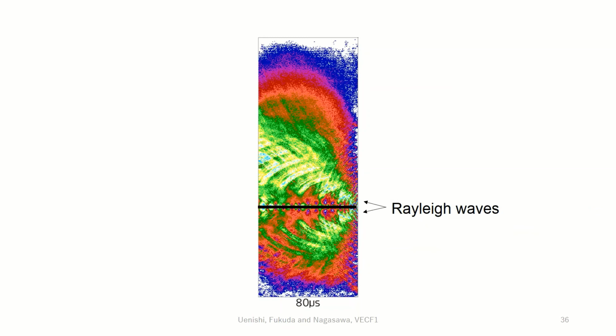Upon total split of the specimen by the primary fracture, Rayleigh surface waves are generated and propagated upwards and downwards along the vertical free surface. The surface waves will move to the edges of the specimen, be reflected and then diffracted to cause further fracture, or more exactly, the resumption of propagation of the arrested secondary fracture, at a later stage.